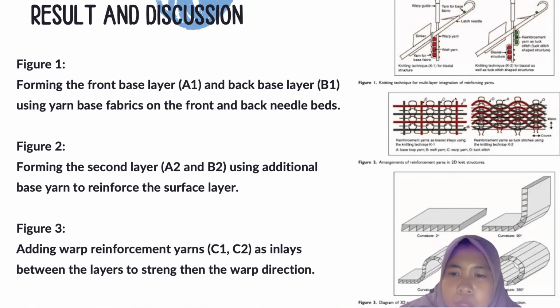Two configurations are the biaxial inlay structure, where reinforcement yarns are inserted in both warp and weft directions, and the tuck stitch structure, where reinforcement yarns are integrated vertically between loops using a tuck knitting technique. The biaxial inlay configuration provides enhanced tensile and flexural strength due to bidirectional reinforcement, while the tuck configuration offers moderate strength but superior impact resistance by improving interlayer connectivity and energy absorption.